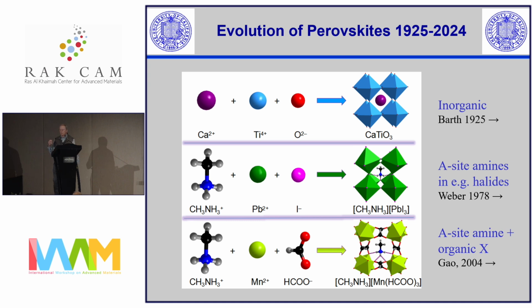And then the next evolution was with Song Gao's group in Beijing. He's no longer in Beijing, he's at Sun Yat-sen University now, the president, where they replaced the linker. So instead of having, say, oxide linkers or halide linkers, they made polyatomic linkers, and in particular the formate. So they made things like dimethylammonium manganese formates, ABX3 formates of that type. And we've done a lot of work on those. They're very interesting. We discovered that they're ferroelectric and multiferroic, and I've talked about this in this forum previously, so I'm not going to discuss that today.